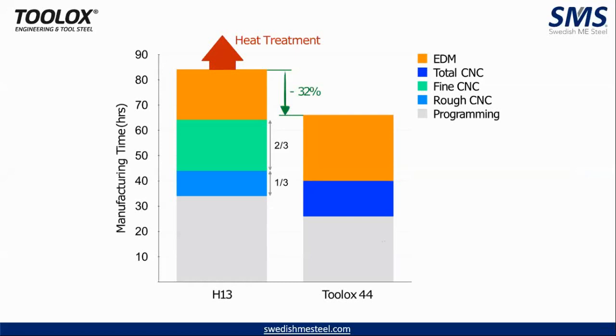And obviously the CNC timing and EDM time are higher since it is a high hardness material. But what you have at the end, the time required from the raw material to the final product, is such that you will be able to save at least 25 to 30% of your manufacturing time. And that would be a welcome benefit. And what you have after heat treatment is an added benefit: your heat treatment time and heat treatment cost involved. But this benefit it can give you right away in manufacturing using this pre-hardened tool steel.